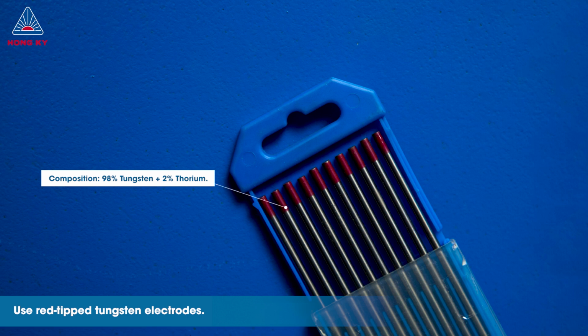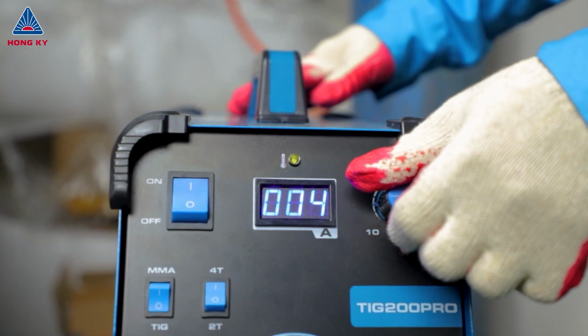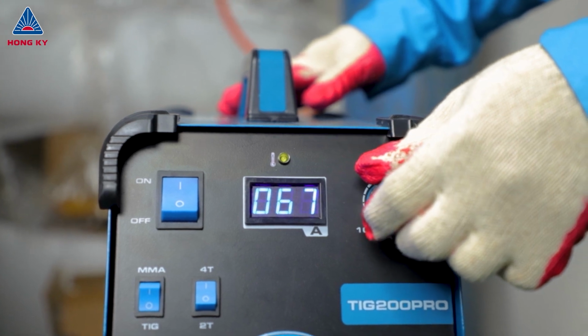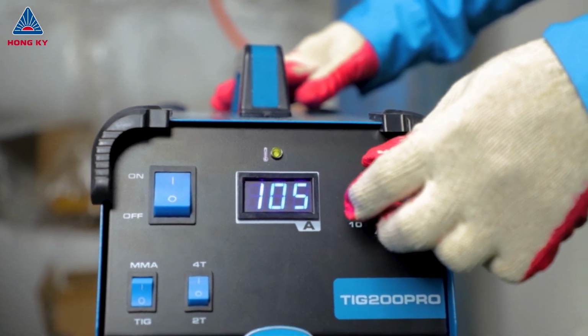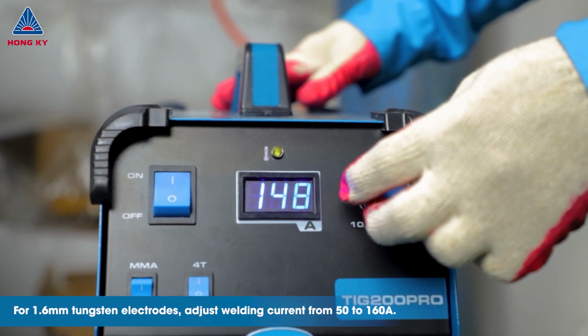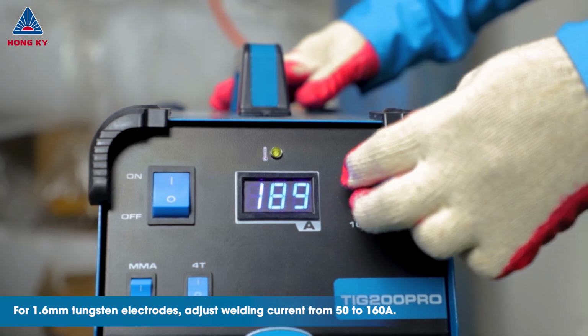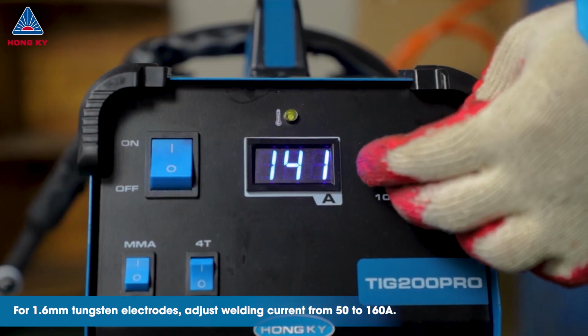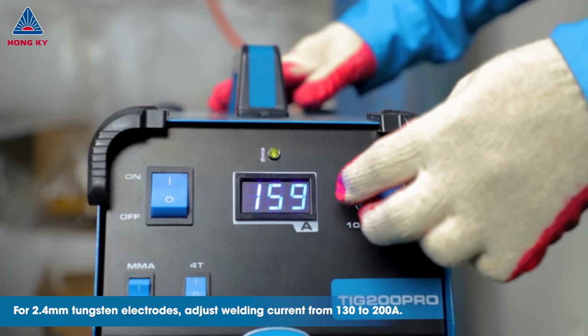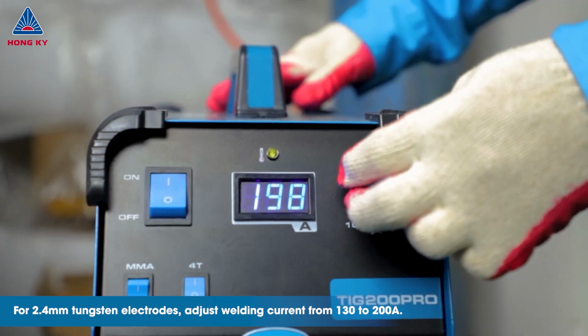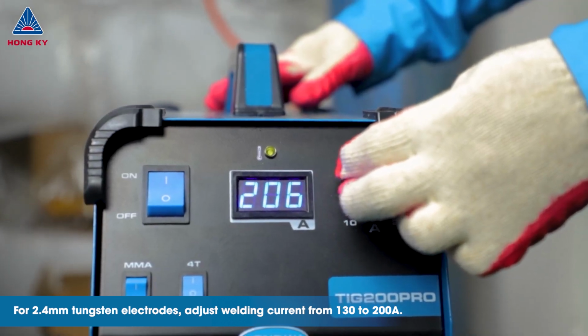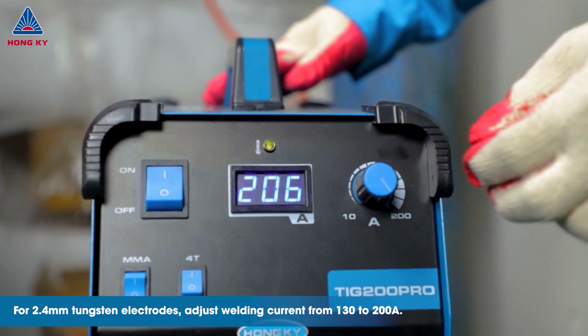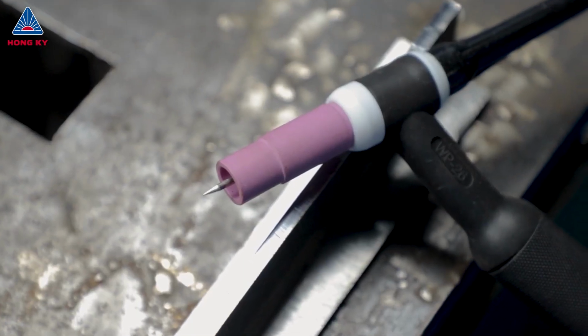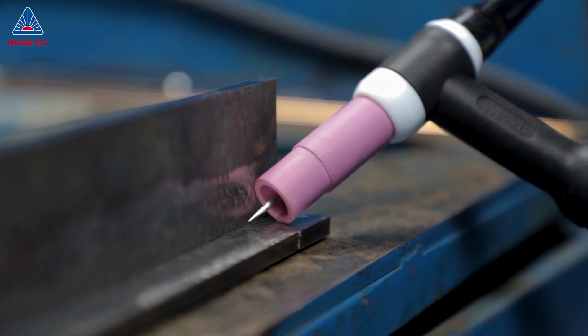During welding, adjusting the current is crucial. With the TIG 200PRO, when using a 1.6mm electrode, you can adjust the current from 50 to 160 amps, and from 130 to 200 amps for a 2.4mm electrode, depending on your skill level and the desired weld penetration. For corner TIG welding, the electrode extension from the gas cup to the tip should be about 2 to 3 times the diameter of the electrode.